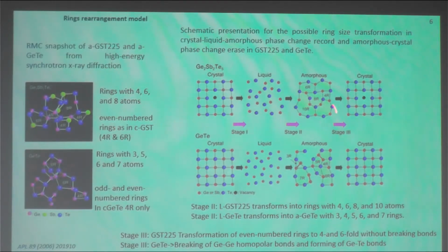If you achieve high cooling rates, we can get the amorphous phase, which consists of 4-fold, 6-fold, 8-fold, and 10-fold rings. Then in stage 3, these even-numbered rings transform to the crystalline state without bond breaking. In the case of germanium telluride, the situation is a little bit more complex, because there are odd rings like 3, 5, and 7. On the way from amorphous to crystalline, the germanium homopolar bonds should rearrange to germanium telluride bonds and then form the crystal structure.